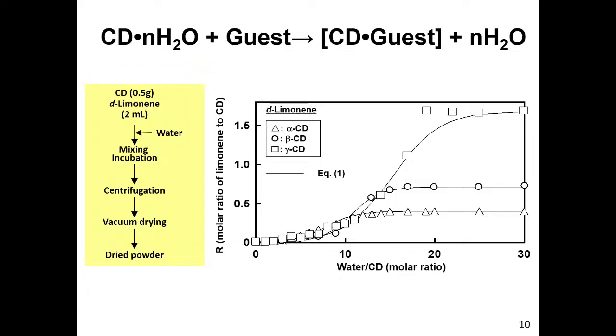So the alpha, beta, gamma inclusion ratio of D-limonene to the cyclodextrin depends on the cyclodextrin cavity size. But this inclusion ratio also depends on the addition of water.